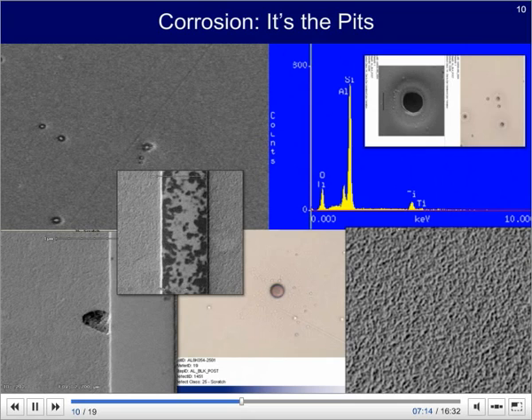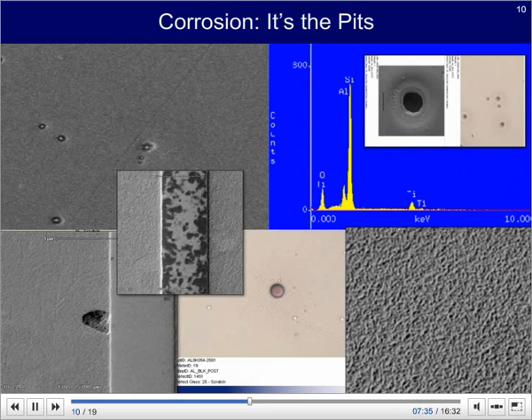A common failure mode in reactive metals is corrosion. Corrosion is largely a chemical or electrochemical phenomenon, made worse by lower pH and higher oxidative environments, though stress from mechanical processes and microstructure are important. Often corrosion appears as localized pits, though damaged edges on lines can be observed. A good way to reduce corrosion is to protect the surface with chemicals that inhibit oxidation. As is often the case, too much protection can slow down polishing rates.